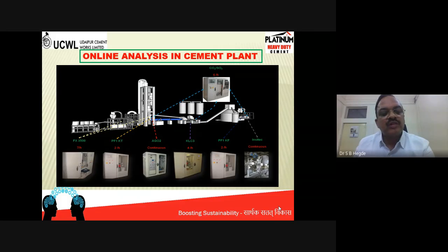So one is for the chemical analysis of raw meal, which is a semi-finished material. Raw meal is nothing but the mixture of limestone and clay and iron and silica material. So that is raw meal, or kiln feed. That means this powder is going inside the kiln for the burning process. So that is also being analyzed online. You can see the first box.